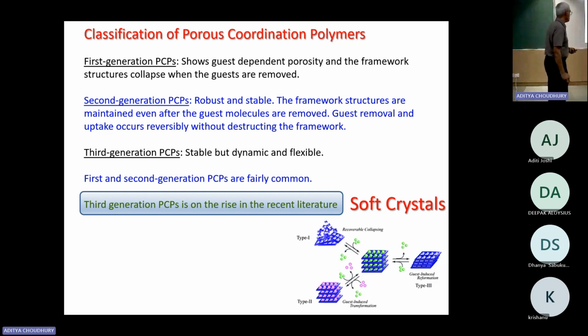So that is recoverable. No, this is soft crystal. It's type 3, type 1. Okay, collapsing. It collapses when the guest is removed, but when you put the guest back, it goes back. That's type 1. Second generation, robust and stable. The framework is maintained. That means nothing happened to the framework. The single crystal may be destroyed once you remove the guest, it may not maintain. But if you record the powder pattern, it will be retained. So you can recover. You can just put it back and everything is retained. There's a third generation.